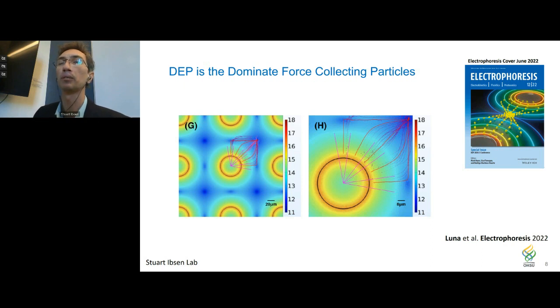And this is really amazing for us to see, because you can see in this region here, there's a local minima of the electric field. So there's a low region where we would expect particles to migrate towards and then get trapped. And then there's a global minima here at these really dark regions in between the electrodes. One of the things that was really amazing was seeing these particles actually move along these lines and make this sharp right-hand turn, as we would expect, because they're going from a global minima to a local minima and then to these high regions. And they can go in the opposite direction as well in negative DEP.